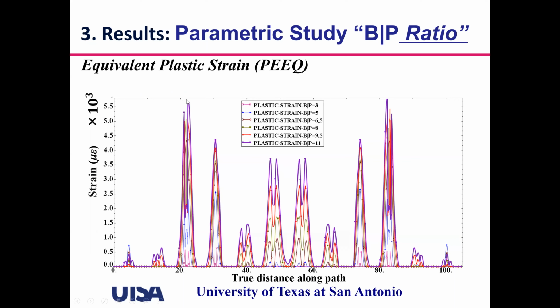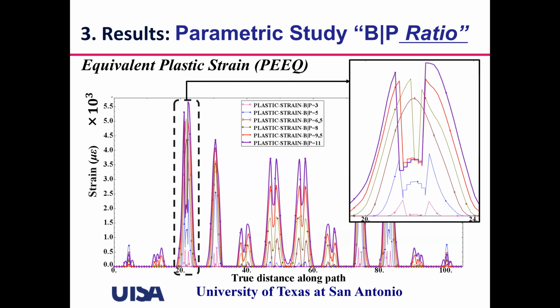So you can see that the largest spikes are for higher values of B/P ratio. When you have a B/P ratio of 11, you have this purple line, which indicates the highest spikes. And then for lower values of B/P, the stress demands are lower. And this is just a zoom to indicate the same observation, that PEEQ, which is the equivalent plastic strain, increases with the B/P ratio.